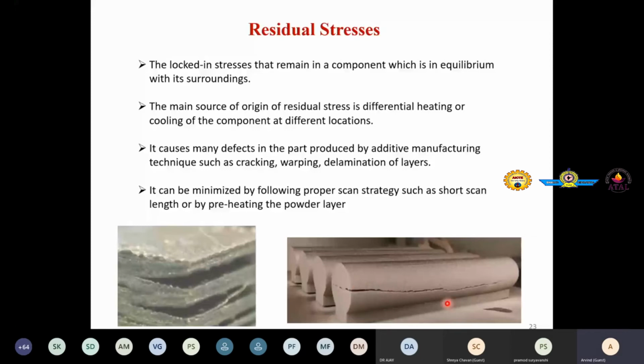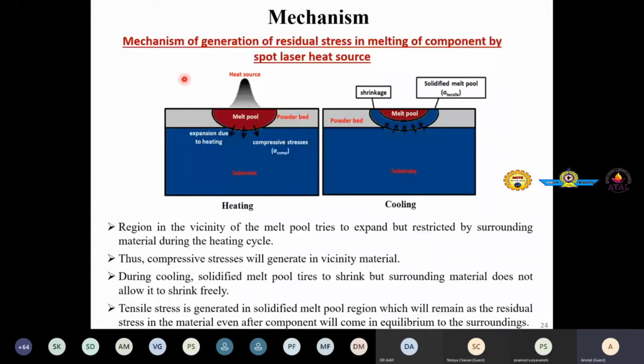So the mechanism of this residual stress, why differential heating and differential cooling lead to residual stress formation, is being explained here. You see, at a local melt pool, when the laser falls on it, the melt pool will form. At the edge of the melt pool, due to heating, expansion of material happens. Because of that, the surrounding material experiences compressive stresses due to an opposing effect. So during heating, we experience expansion near the melt pool boundary, and below that, a compressive stress.